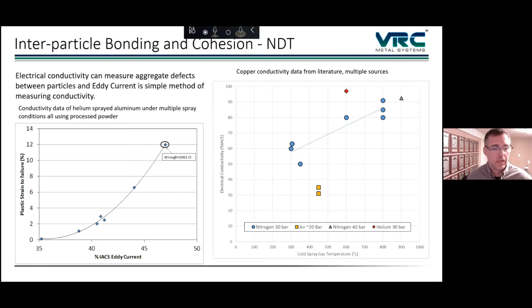Now on the right, you see copper, and it's a similar trend. As you increase the gas temperature at the bottom, or you increase the pressure, which is the difference between the yellow and the blue, well, first of all, it's air, but it's also higher pressure, going to the 30 bar, which is the blue samples. And then you see helium. If you use helium, which is a much higher velocity gas, you can get up to 99% at even lower temperatures. So there's a profound effect on the conductivity of the material when you increase the velocity of the particles.